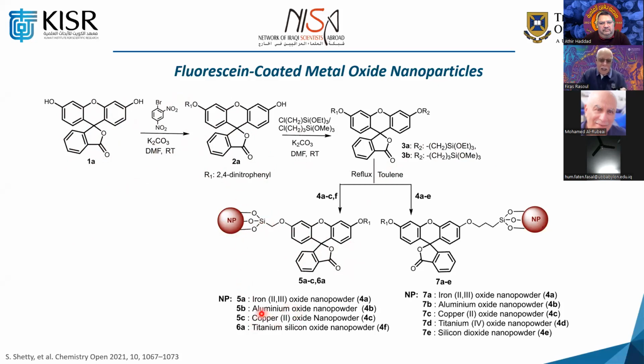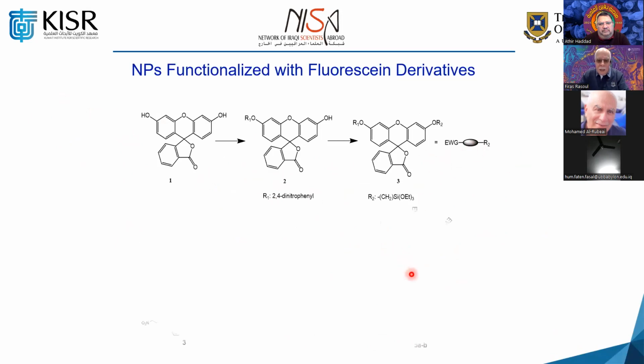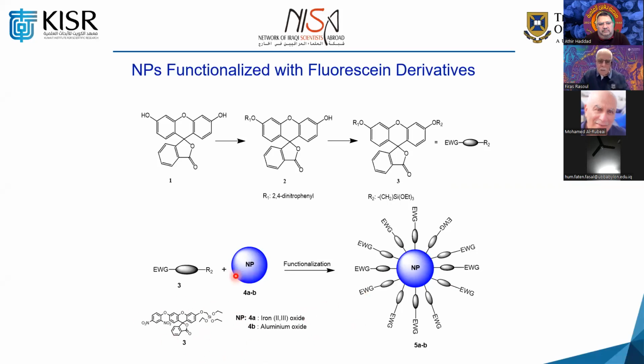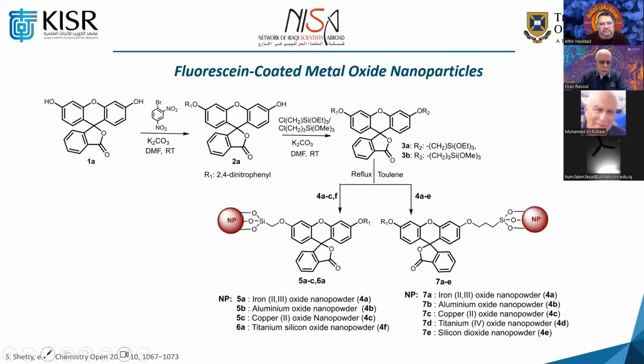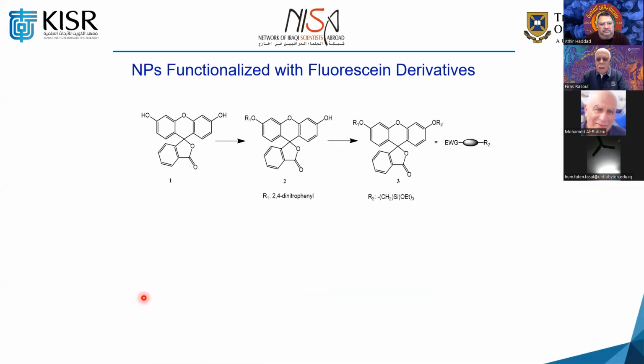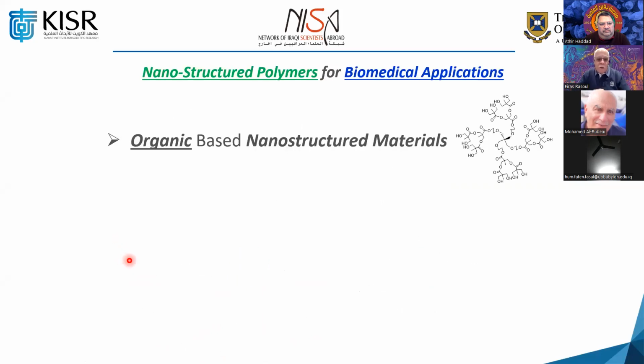So they used iron oxide, aluminum oxide, copper oxide, titanium silicate, a variety of them. And of course, if you look at that group, R1, which is a dinitrophenyl group, this is where, when you expose it to H2S, it will convert to an amine and become fluorescent. So we could quench the fluorescence by doing this reaction, but then when you react with H2S, it will reinstate the fluorescence. And really, this is what happened. This is just giving you an example of that. By the way, this has been published recently, in 2021. Okay, so this is another approach for that.